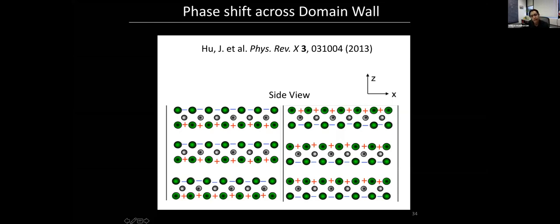However, one interesting thing about this idea is that if you could find a sort of domain wall in the system where the top and bottom seleniums are flipped, and this is what I was talking about at the beginning of the talk, you should actually expect to see these kinds of domain walls. Then you naturally have a pi phase shift in the superconducting order parameter.